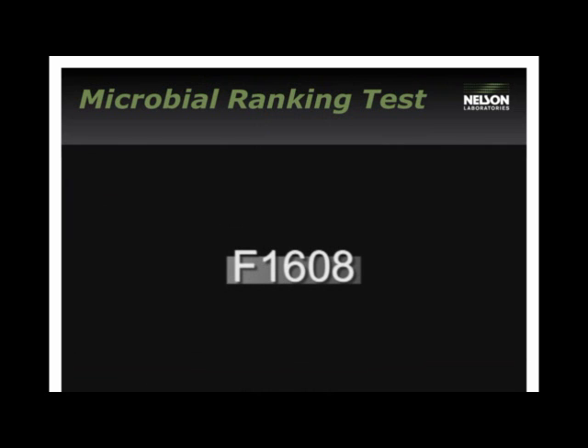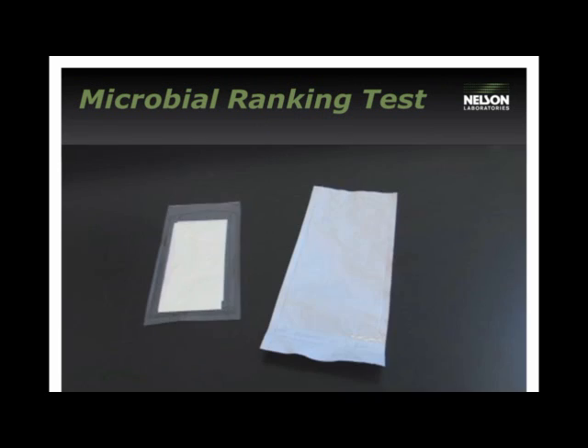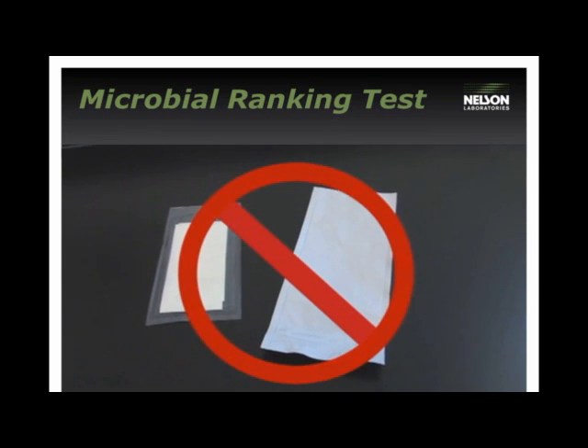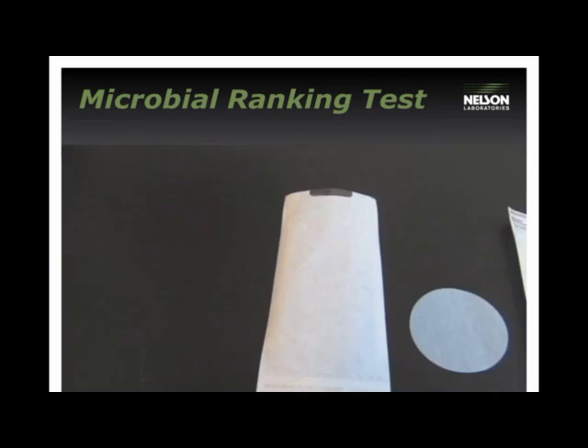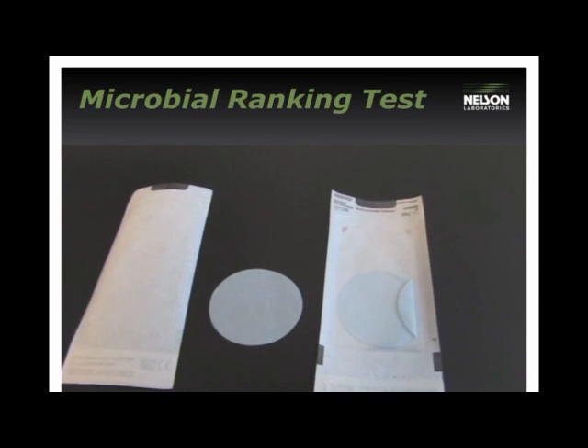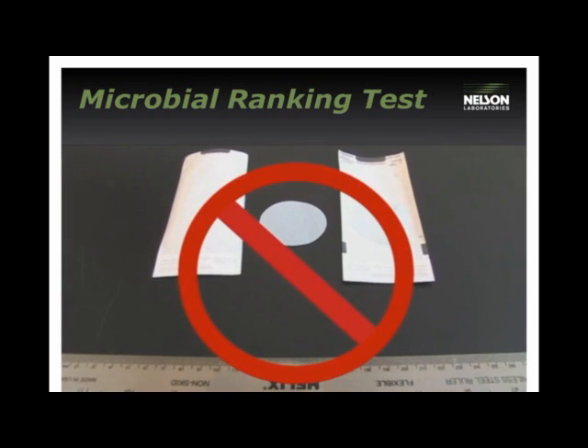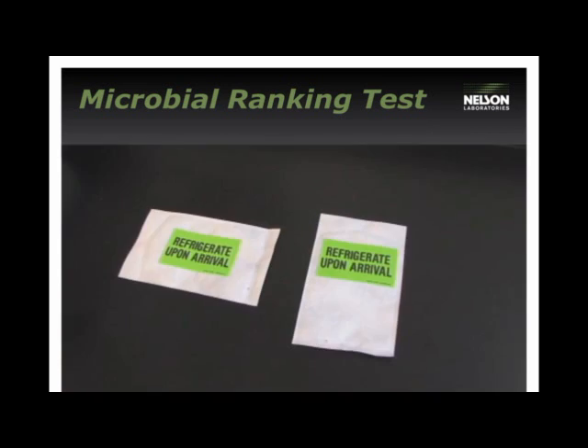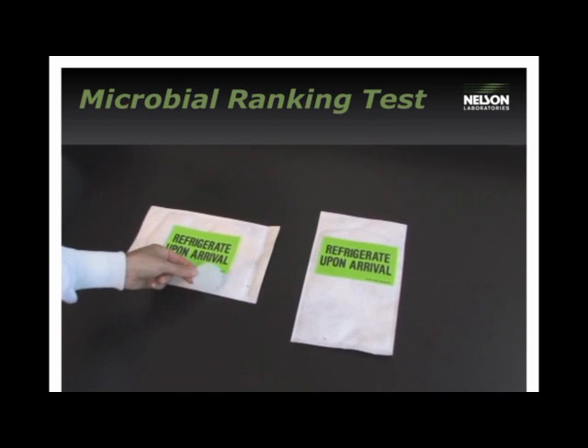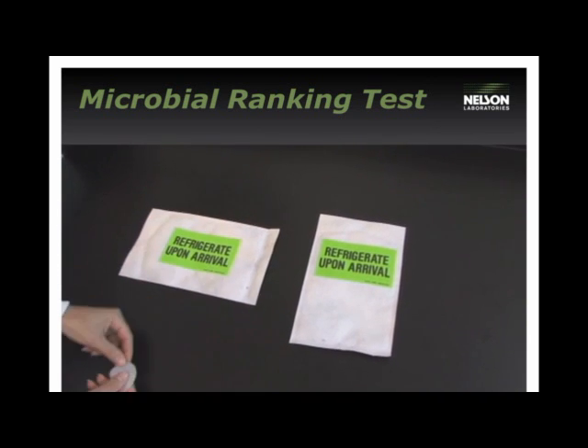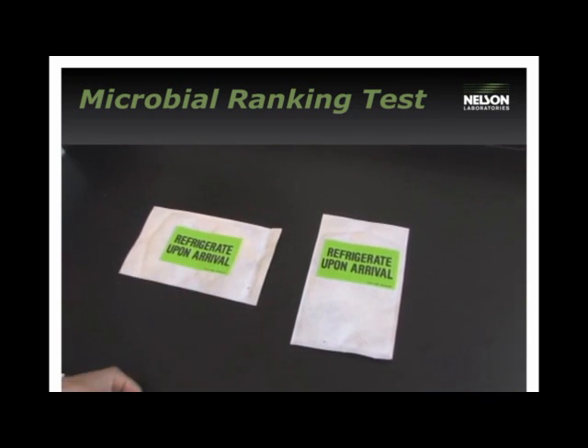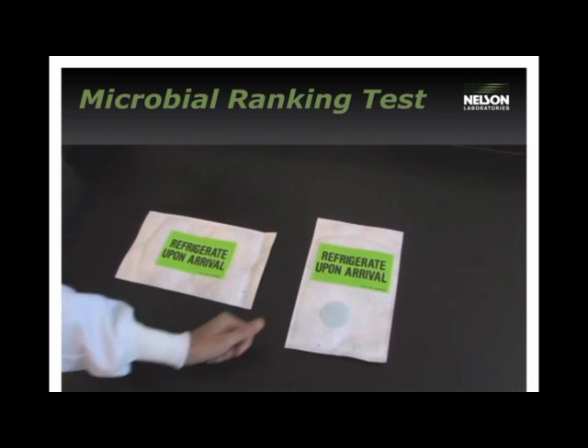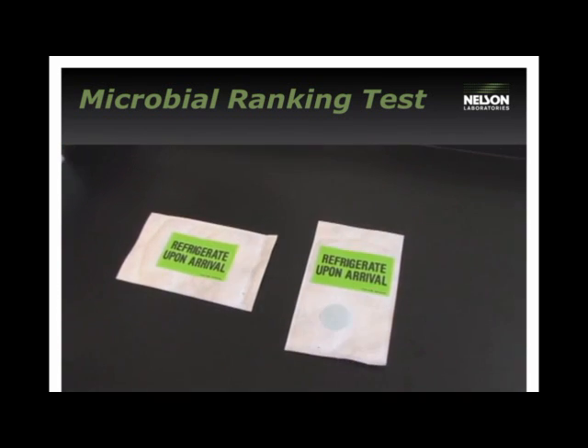ASTM F1608 is a microbial integrity test for porous materials only. Foils and films cannot be tested with this method. Samples smaller than 47 millimeters cannot be tested with this method. Samples with large labels must have an area of at least 47 millimeters of exposed porous material.